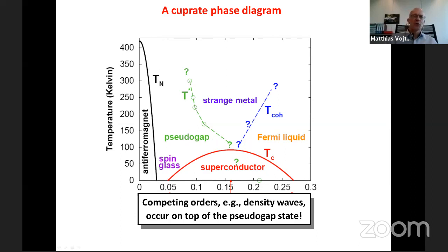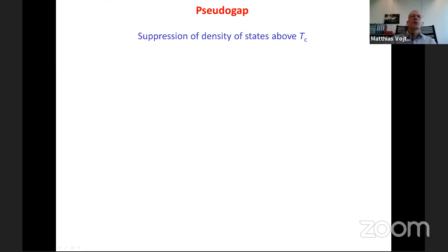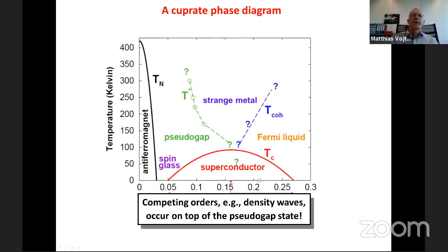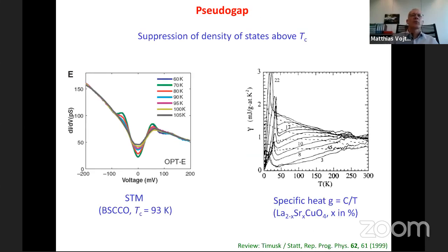So in some sense, the pseudogap is the most interesting and most mysterious property of these cuprates. So what is a pseudogap? The pseudogap essentially refers to a suppression of the density of states in the metallic state, a suppression of density of states above the superconducting TC. And in measurable observables, you see this in these two plots. One shows a tunneling density of states. That's essentially a measure of the local quasi-particle density of states. And this is a material which has a superconducting TC of 93 Kelvin. And at low temperatures, you see a superconducting gap. That's this dip here. But this dip continues to exist significantly above TC. That's what this plot shows.